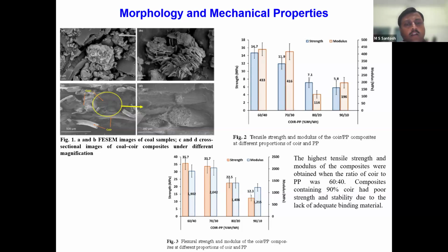And in figure D, you can clearly note that there are several pores available on the surface of these biomass materials. These pores are the ones that provide suitable aeration ability when blended with coal, and also improve the strength, because these biomass materials are used in the form of fibers. These fibrous pores offer suitable strength to the biocomposite material when blended with coal.